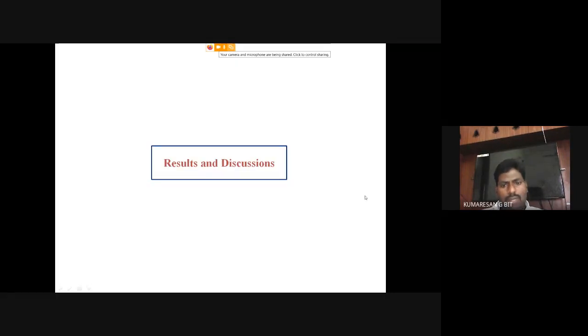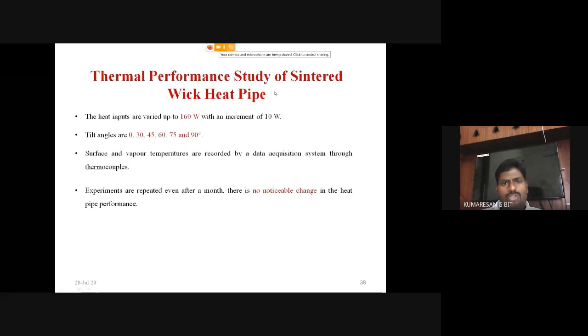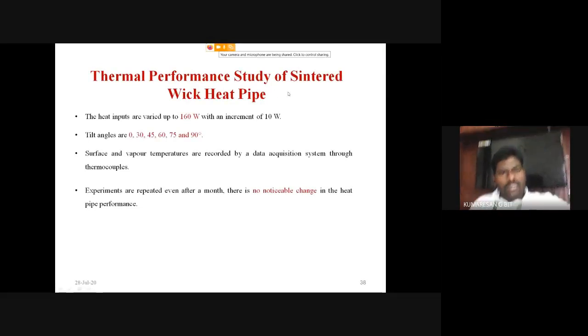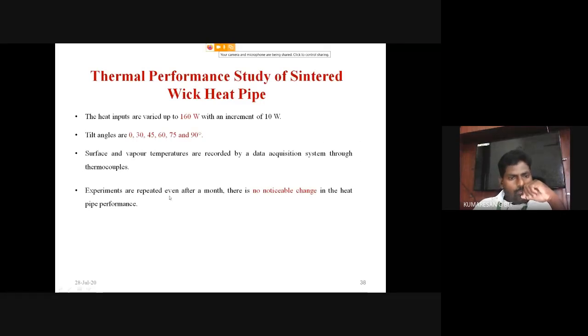Then the results and interpretation of results. The thermal performance study of the sintered wick heat pipe is here. We have already seen that the heat input is varied from 10 watts to 160 watts. The orientation angle of the heat pipe is varied from 0 to 90 degrees. Surface and vapor temperatures are recorded using a data acquisition system through the thermocouples. These experiments were repeated even after a month to confirm whether there are any notable changes in the heat pipe performance.